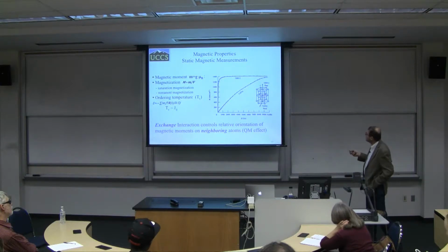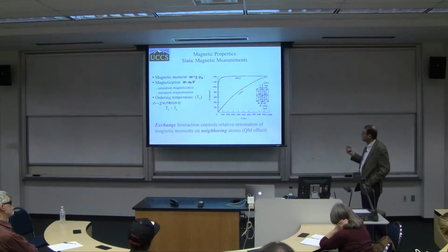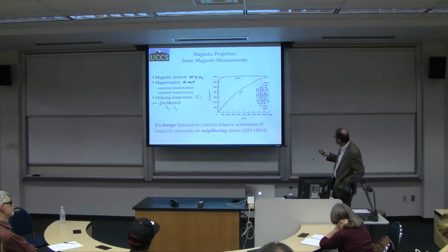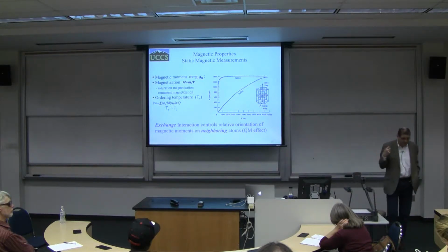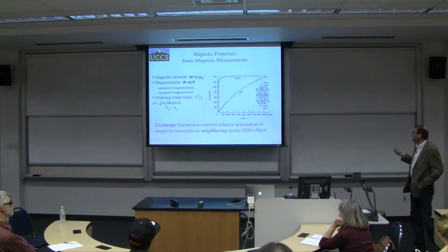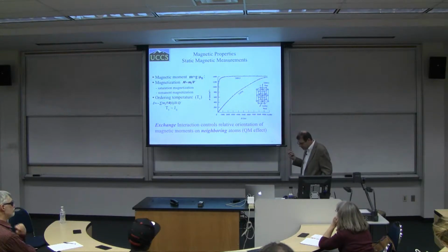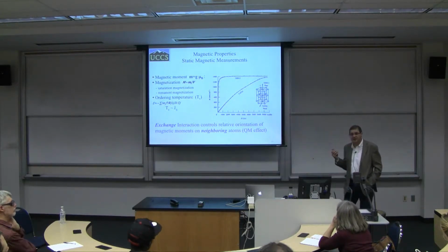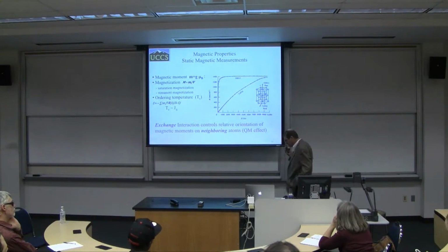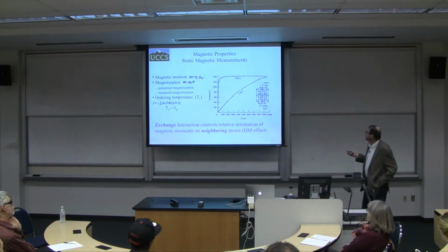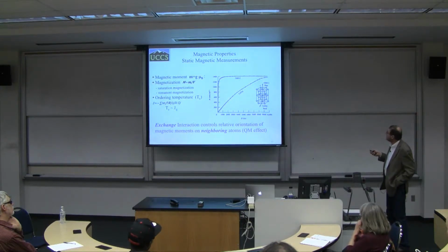And if I change the direction, the behavior is very, very different. This simply tells me that this particular sample is very anisotropic. Depending on the direction in which I am performing measurements, I have a different value of M. In some particular applications this is extremely important; in others, it is actually undesirable. Basically, what we want to know is how this material behaves in different orientations.